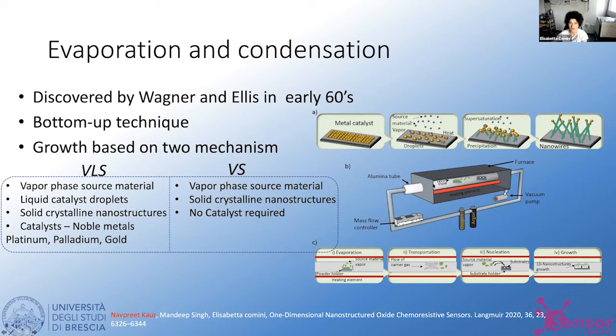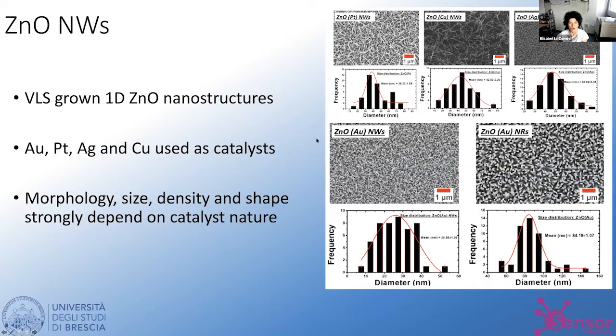You have a flow of normally inert carrier gas. We are using, for example, argon, and this flow is the mass transport from the source to the substrate. Of course, you need to find the right experimental parameters that can give you the one-dimensional growth instead of a particle or a film growth, which is the conventional one. So for each system, for each material, for each catalyst, you will find a special evaporation temperature, condensation temperature, and pressure of the system, since this system is kept at a pressure lower than the ambient pressure.